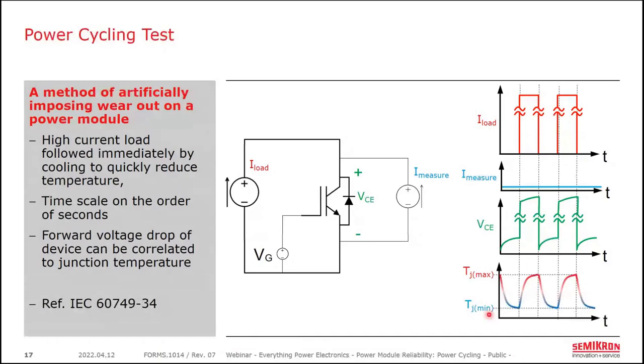Then, going back to this power cycling test, we can continuously pass a very low measurement current, shown in blue, which is not enough to heat the device, but is enough for us to measure the voltage drop across the device. Immediately after that high current pulse, we measure the voltage drop and we get the hot temperature for that temperature cycle. And then as that device cools, we get the cold temperature right before we hit it with another high current pulse. So the device is being heated and cooled and we are measuring a TJ min, a minimum junction temperature, and a TJ max.